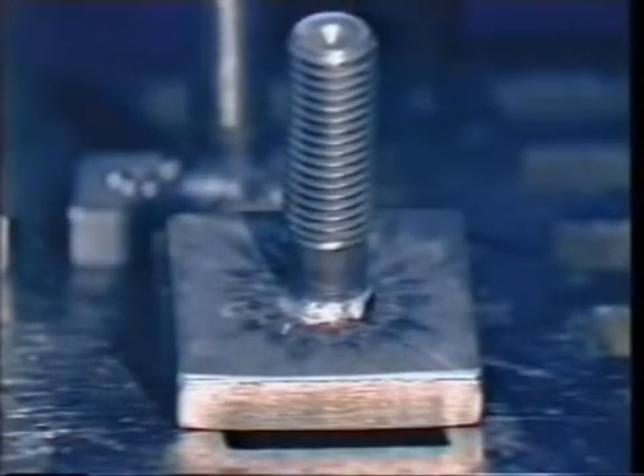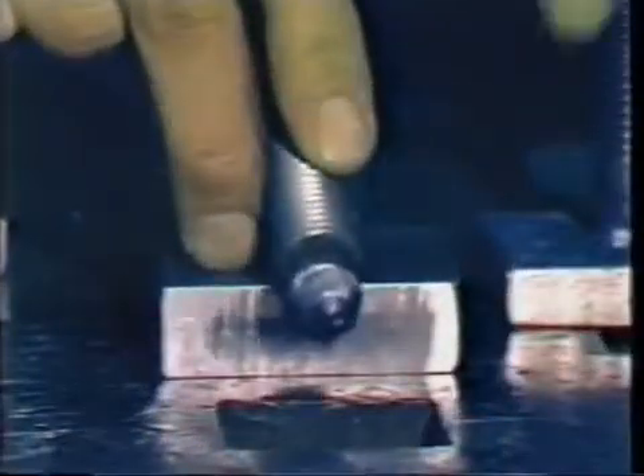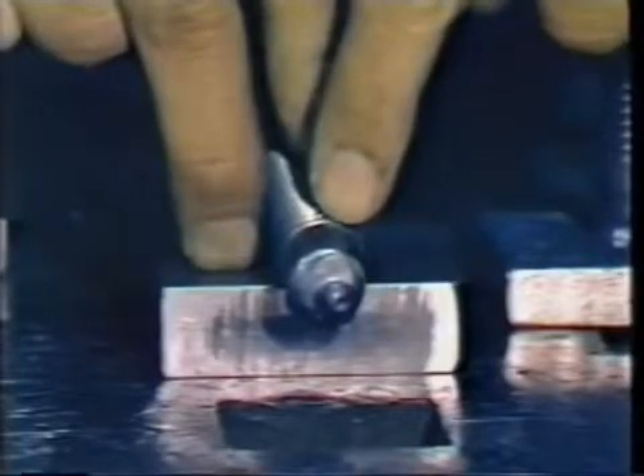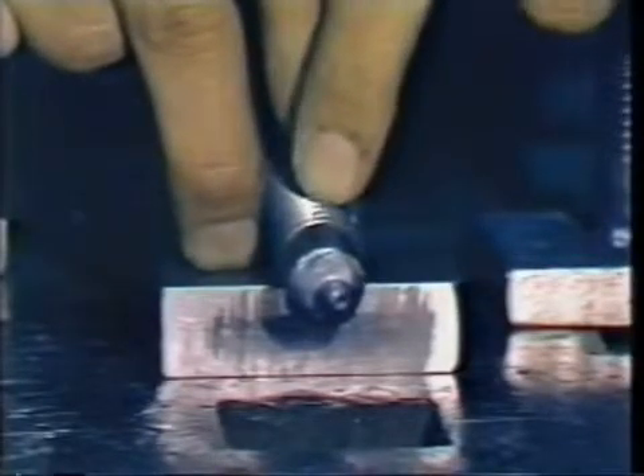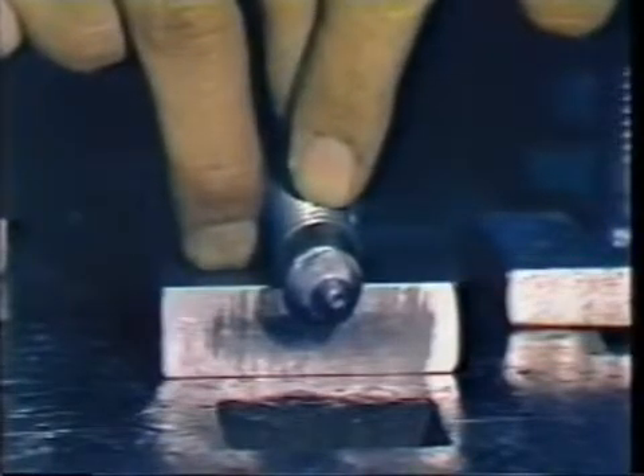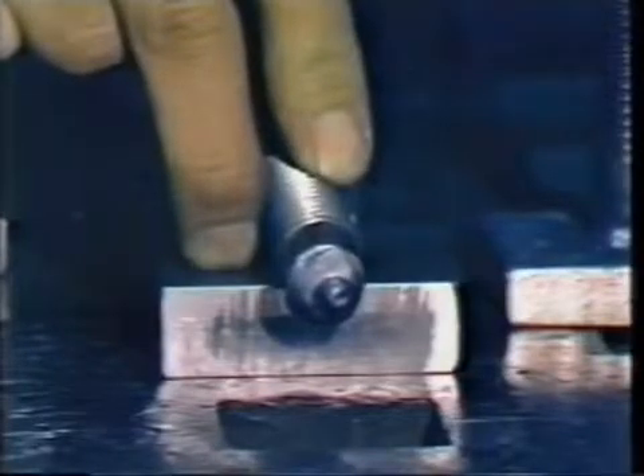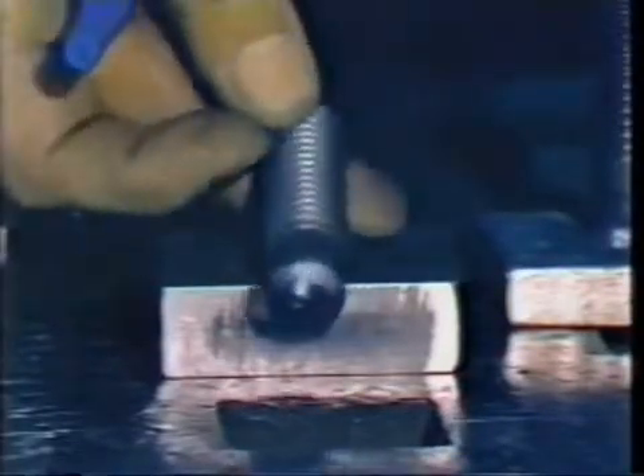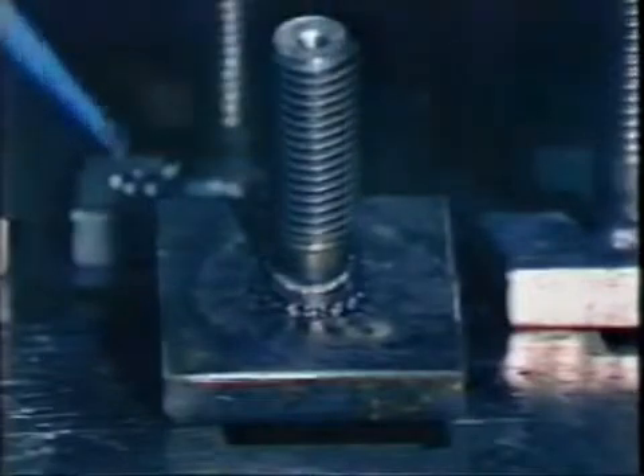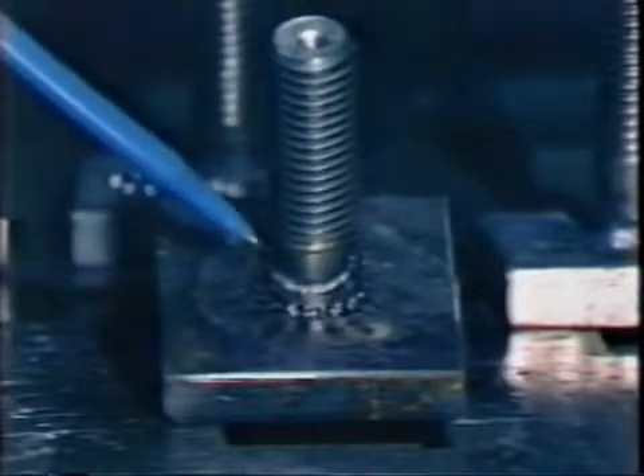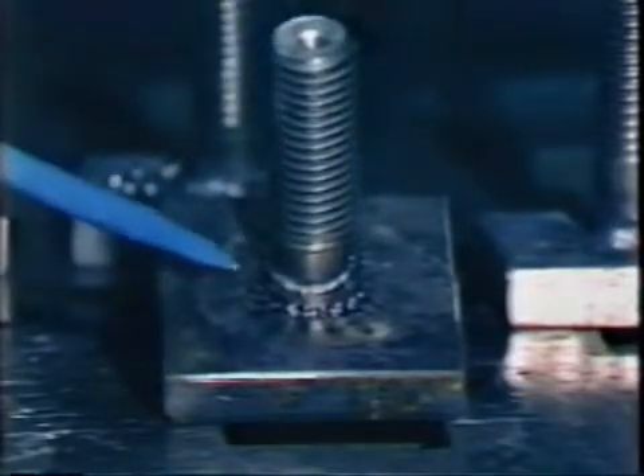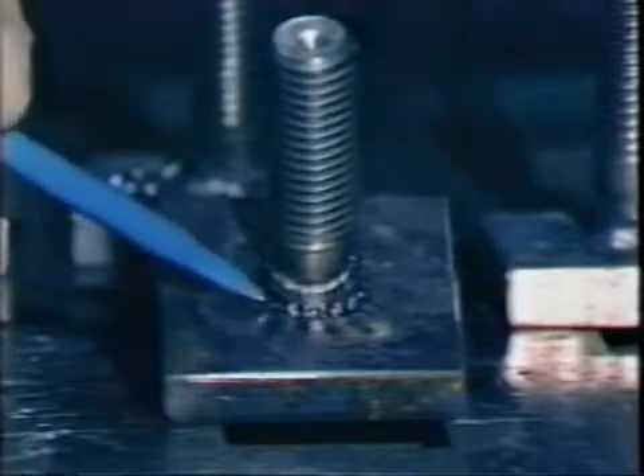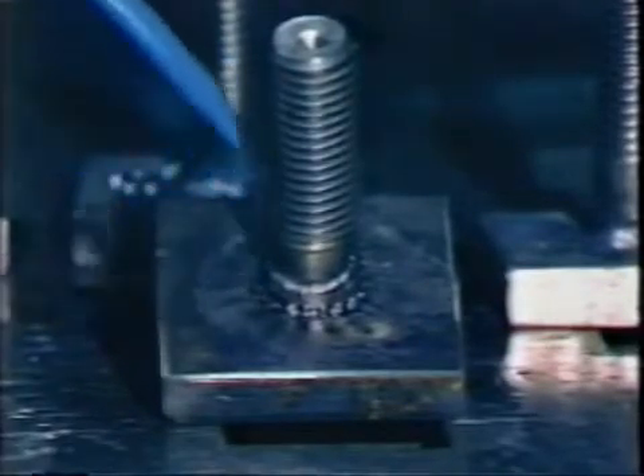The extreme case of a hang-up will just be a stud that comes off in the gun. An operator could get this same effect by lifting the gun off from a welded stud too quickly. Again, the good weld is bright and shiny, with even fillet development and a blend into the base material at the edges of the fillet.